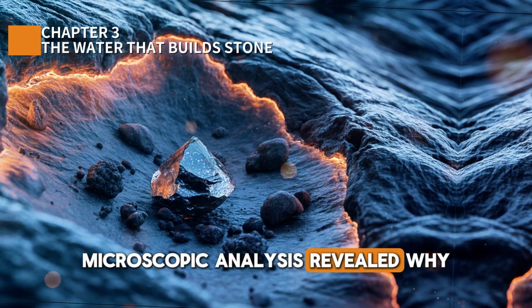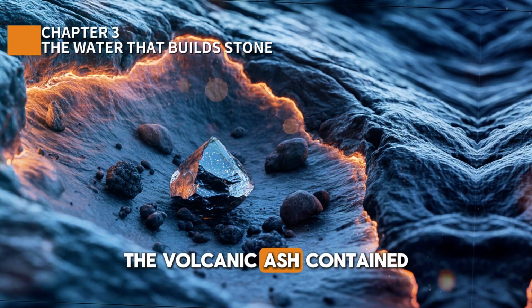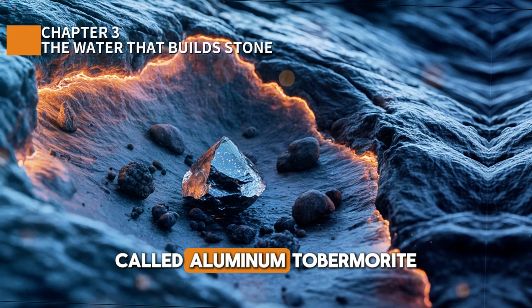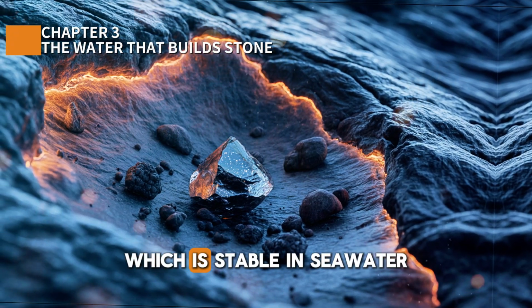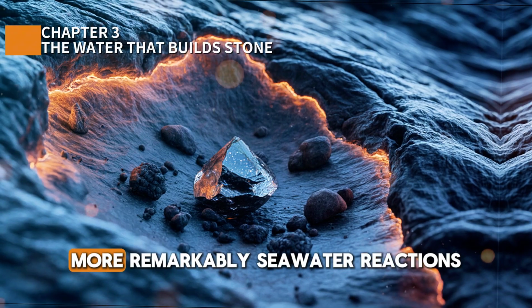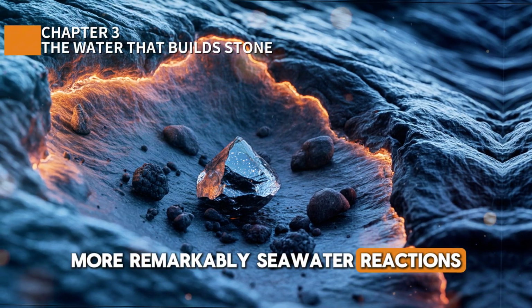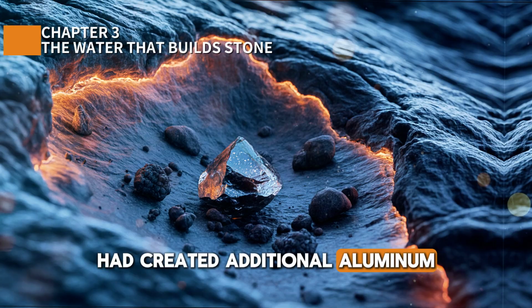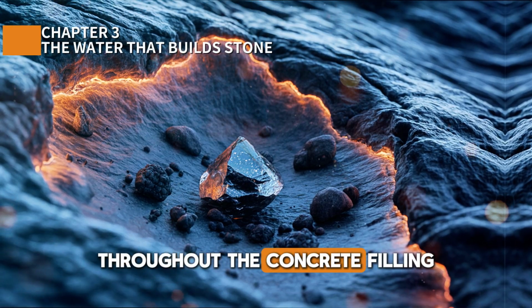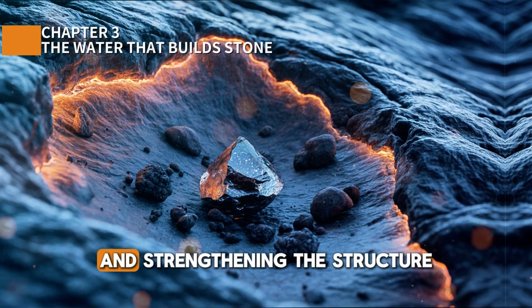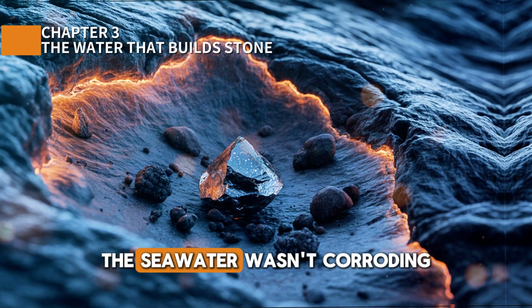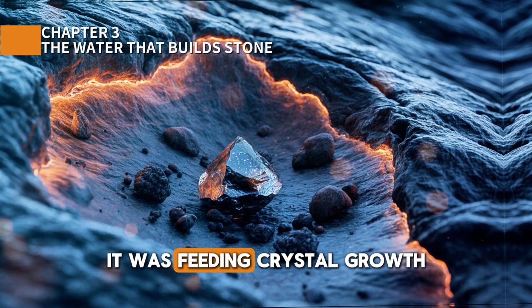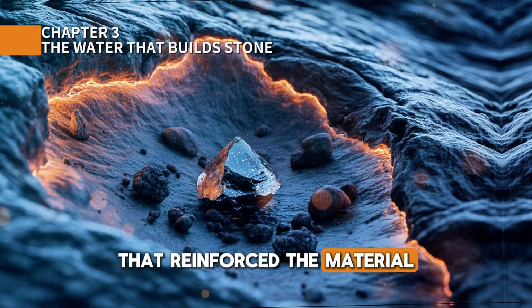Microscopic analysis revealed why. The volcanic ash contained a mineral called aluminum tobermorite, which is stable in seawater. More remarkably, seawater reactions had created additional aluminum tobermorite crystals throughout the concrete, filling microscopic voids and strengthening the structure. The seawater wasn't corroding the concrete, it was feeding crystal growth that reinforced the material.